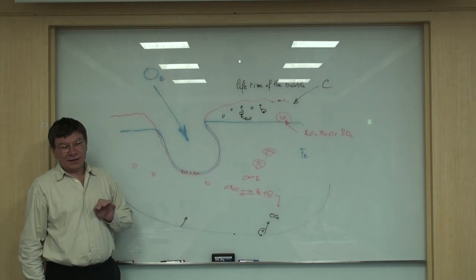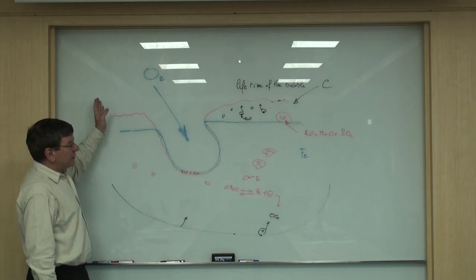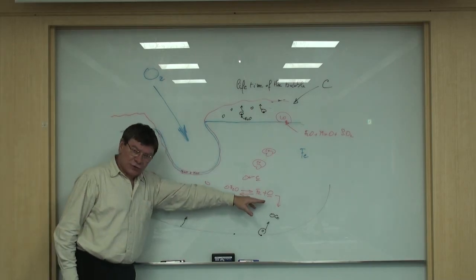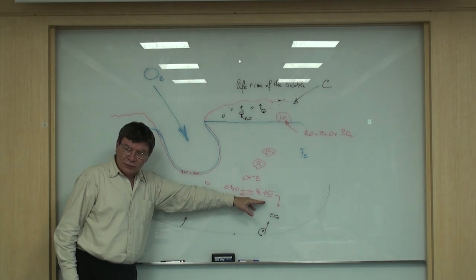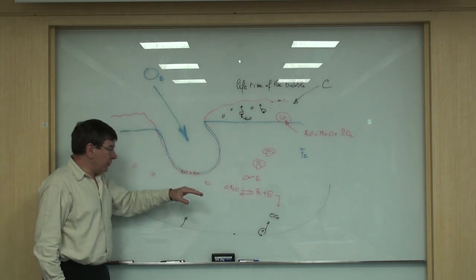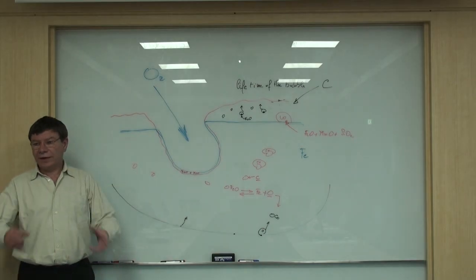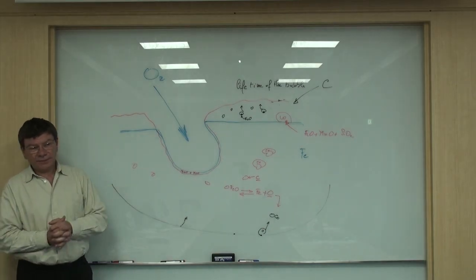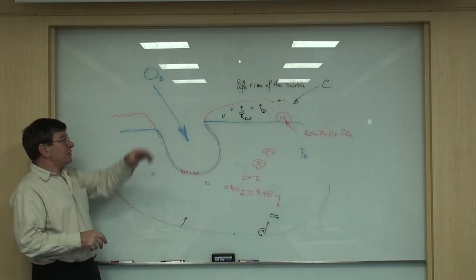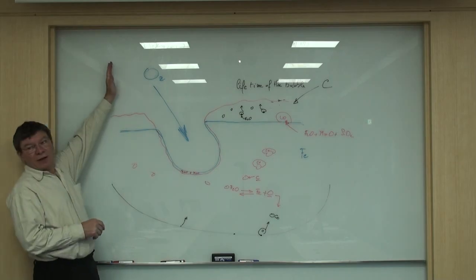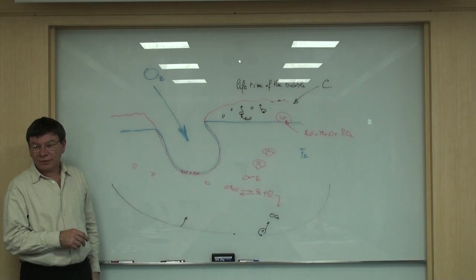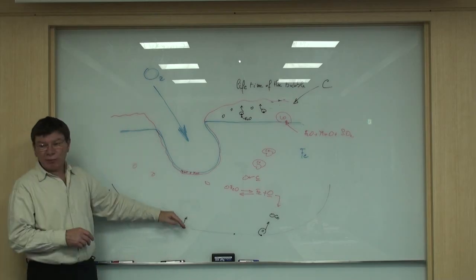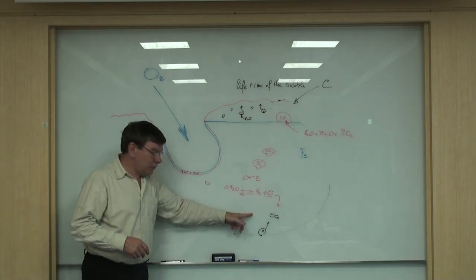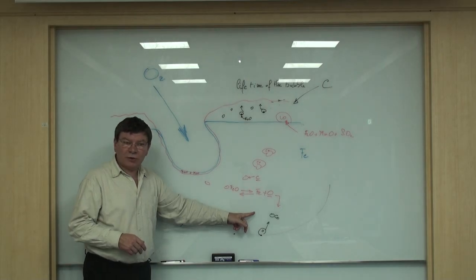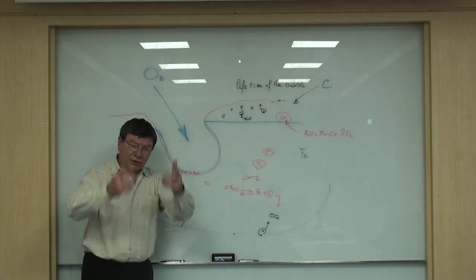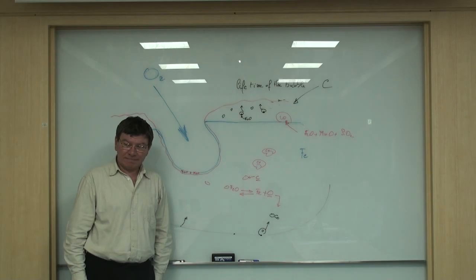Same at the later stage, because oxygen solubility is also related to temperature. If you have reached 1580, 1590, 1600 degrees C, and you still have a bundle of scrap hanging to the wall, which is falling down into the bath, then of course temperature drops immediately, and you force the oxygen to come back to the equilibrium very rapidly, so you get a reaction. Okay?